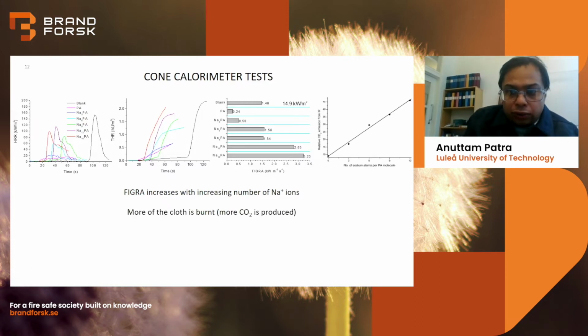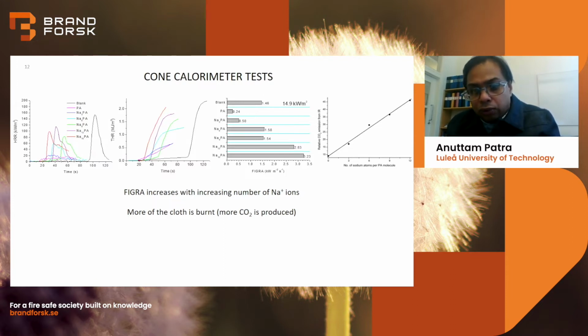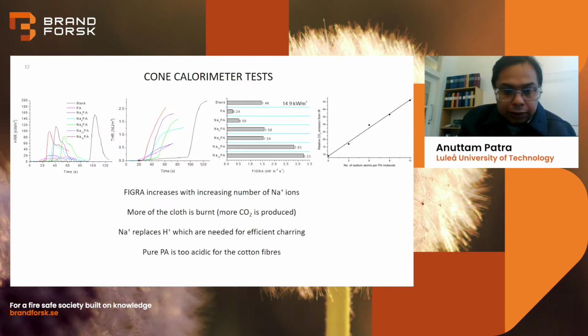We also saw the cloth burns more and more with increasing sodium, because we can see more carbon dioxide is produced. We measured that by analyzing the evolved gas from the cone calorimeter with an FTIR spectrophotometer. It happens because when we replace the acidic proton with sodium ions, there is less acidity. So the cotton cloth gets less charred, and less charring causes more burning.